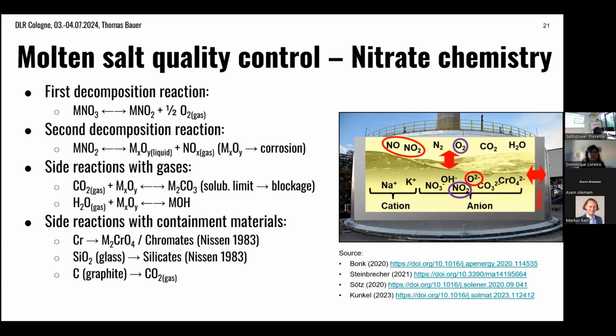The oxide ions will dissolve in the salt, and they are typically attributed to cause the corrosion. And you also see at the same time some nitrogen oxide formation and decomposition. But Frerk already introduced this. There are also other side reactions.